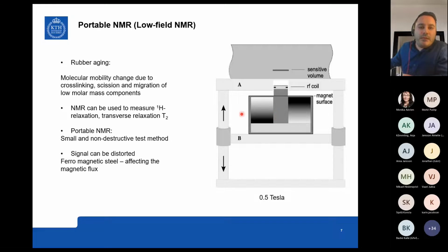So what we do is that this sample, which is on the sample holder, so essentially the protons. If you imagine the protons here at this location, which is 5 millimeters from the surface, they are all in the direction of equilibrium, I would say. And as we induce a current through that coil, we're going to create a magnetic field which is perpendicular to that external magnetic field from the magnet. So we're going to push the protons essentially out of equilibrium. And when we cut off the current, these protons are going to relax back to the equilibrium position. And essentially the time of relaxation is the transverse relaxation time that we're looking for.